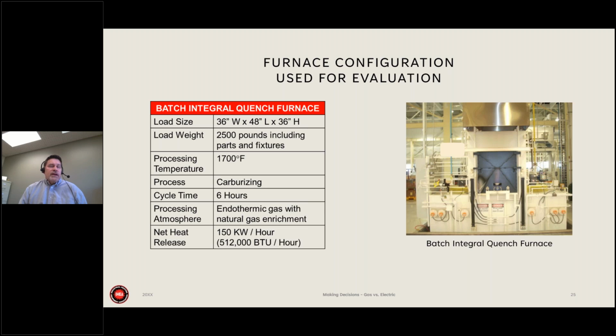The furnace used in the evaluation of the data I'm going to share was a 36-48-36 hot zone size, and the load weight was 2,500 pounds, including the fixture and the parts. So that's gross loading. Operating at 1,700 degrees, carburizing for 6 hours, and I mentioned the process atmosphere already, with a net heat release of 512,000 BTUs per hour.